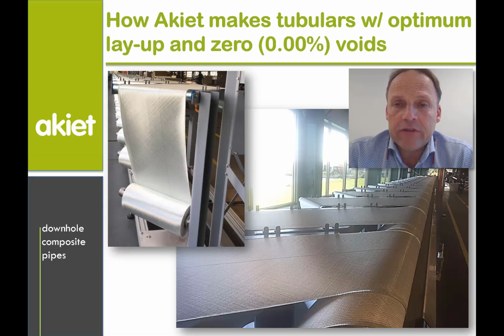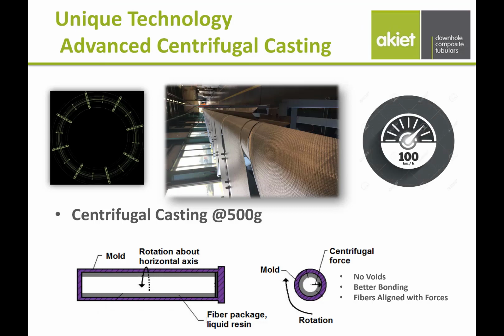Now this looks different. This is how Akiet makes its tubulars. This works in a dry state, and the material there is the glass, which has the glass fibers running in different directions, over which we have full control. It's placed within a mold, and subsequently the mold is centrifuged. It's rotated at very, very high revs to actually create forces of up to 500 G, 500 times the gravity. So after the glass is placed on the inside of the mold, and it will sit against the surface on the inside, then the centrifuge starts. It really starts rotating fast, very high revs, to generate hundreds of G forces.